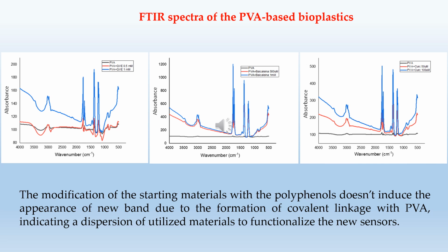Morphofunctional analysis of the bioplastics was performed by means of FTIR spectroscopy. As can be seen from the graph, the modification of the starting materials with the polyphenol doesn't induce the appearance of new bands due to the formation of covalent linkage with PVA, indicating a dispersion of utilized materials to functionalize the new sensors. It is possible to notice mainly the appearance of a broad and intense band at about 1600 to 1700 cm-1, characteristic of the functional group present in these natural compounds.